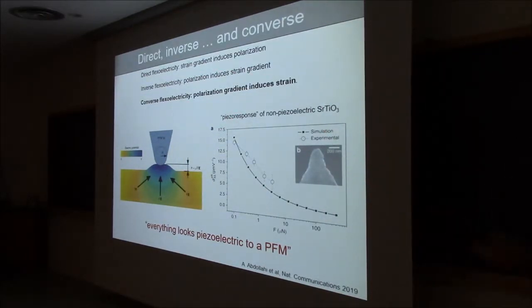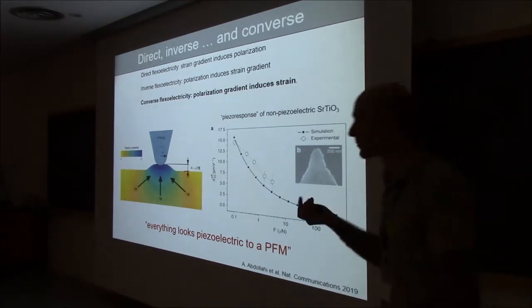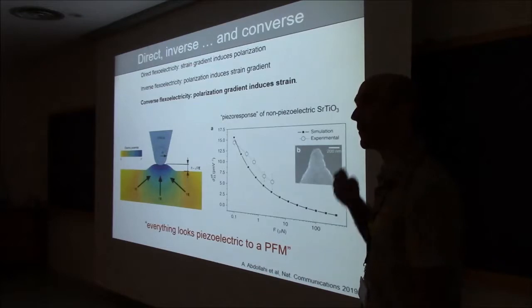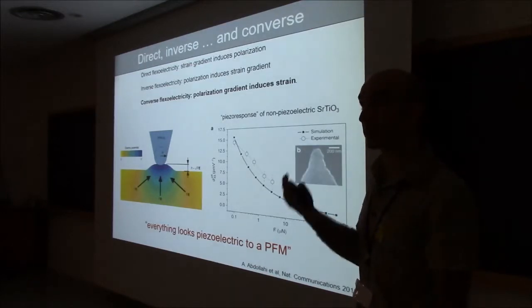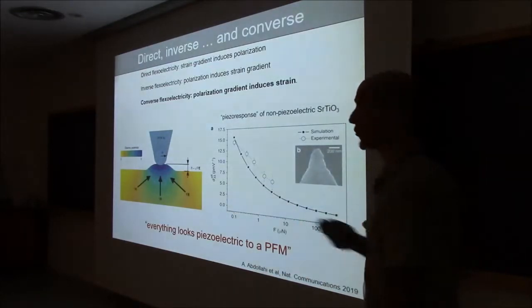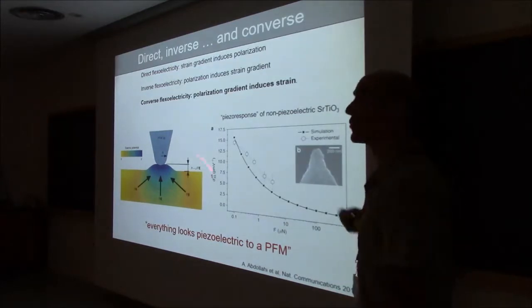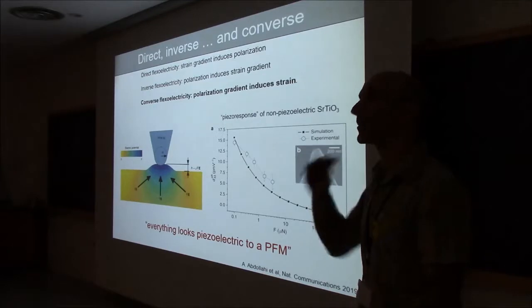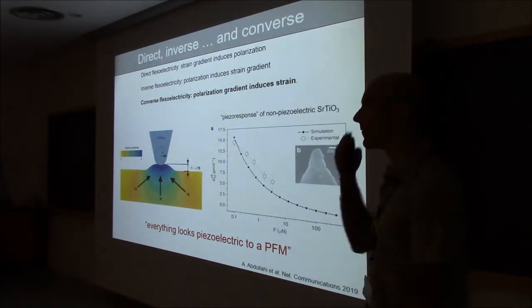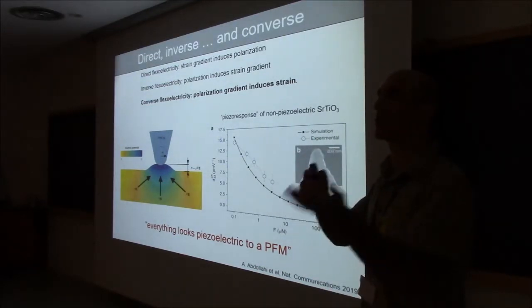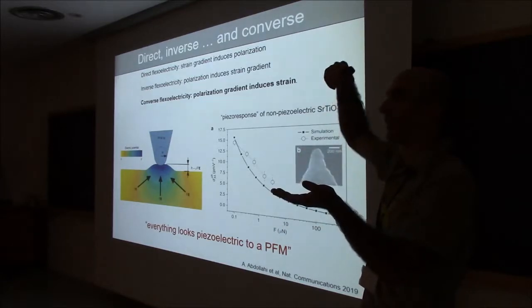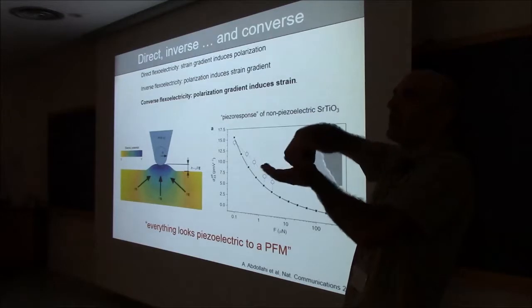And this effect actually is quite important. You're going to have a talk about PFM, I expect, next week by Celine, and hopefully she's going to tell you about artifacts that can happen in PFM, piezo response force microscopy. I would like to mention this one because it's one that will always, absolutely always be present. If you have a PFM, for those of you who don't know this, piezo response force microscopy, basically you have an atomic force microscope, the metallic tip that you put in contact with your material, and you want to determine whether that material is piezoelectric or not.